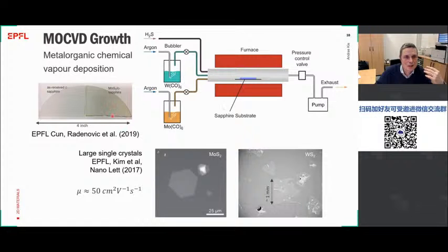So this we can grow on a wafer scale, molybdenum disulfide. For example, here are some examples of also molybdenum disulfide and tungsten disulfide, which have been grown with a large grain size, on the order of even up to 1 millimeter in the case of tungsten disulfide. And this is probably, in my opinion, the most promising approach for going to these materials on an industrial scale. First off, because that's also the approach which is used for many other compound semiconductors, so the equipment is already mostly there. And also, the advantage of this technique is that it very easily allows you to do doping, make heterostructures, etc., and you don't run out of materials like in the case of powder-based CVD growth.